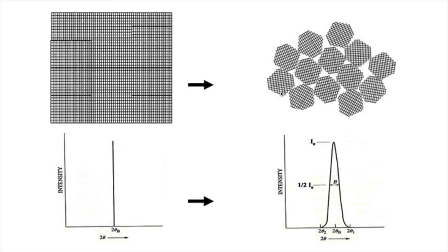Now, let's say I have another particle, but that particle is actually composed of a number of much smaller crystals. So something like this. If you're looking at this under a light microscope, this might appear to be just one large particle, where the diameter is roughly the same as what's over here. But in actuality, instead of one crystal, there are many crystals here, all these different crystals. And you can see that some of them have different orientations than others. So they're both particles, but this particle is composed of one crystal, and this particle is made of multiple crystals.